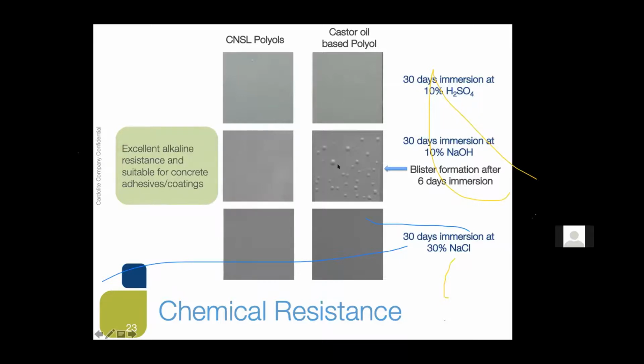And if you look at the comparative castor-based having blisters, when you check 30 days immersion test with the sodium hydroxide, but CNSL polyols have a better alkali resistance. This is another advantage in the polyol. Some of the application area in the submerged pipeline, those kind of application area, you can use this kind of polyol.